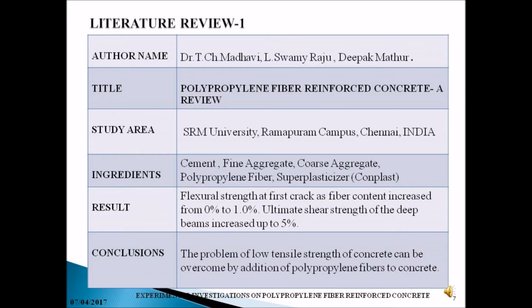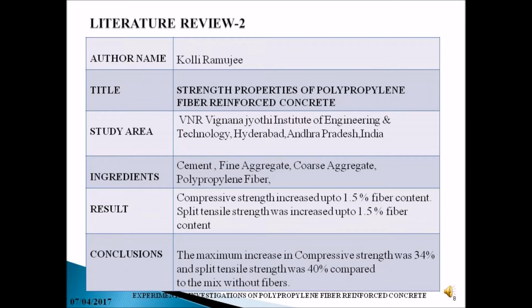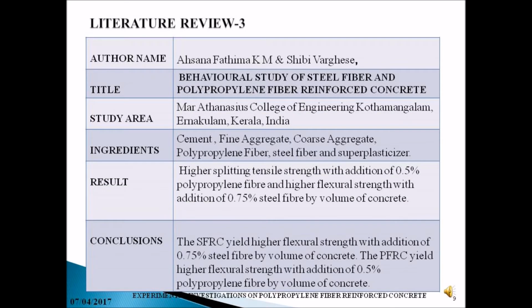Coming to the literature review, number 1 is titled Polypropylene Fiber Reinforced Concrete: A Review. The results are: the flexural strength at first crack increased as fiber content increased from 0% to 1%. The ultimate shear increased up to 5%. The low tensile strength of concrete has been overcome. Literature review 2 is titled Strength Properties of Polypropylene Fiber Reinforced Concrete. The results are compression strength and split tensile strength increased up to 1.5% fiber content. They came to a conclusion that the increase in compression strength was 34, while that of the tensile strength is 40.